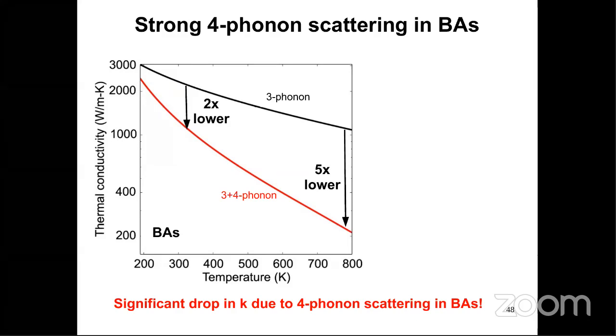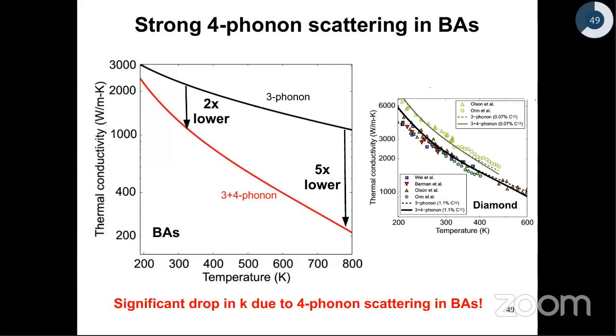So before I proceed, if you remember, I had mentioned that for diamond, we expect 4 phonon scattering effect to be weak because we were able to get excellent agreement with the experiment with just the conventional 3 phonon approach. And that's basically what we get. When we did the calculation for diamond, including 4 phonon scattering, we hardly noticed any change in the calculated thermal conductivity. More importantly, we still got excellent agreement with the experiment over the broad temperature range.